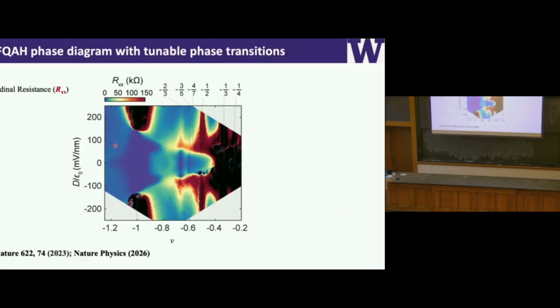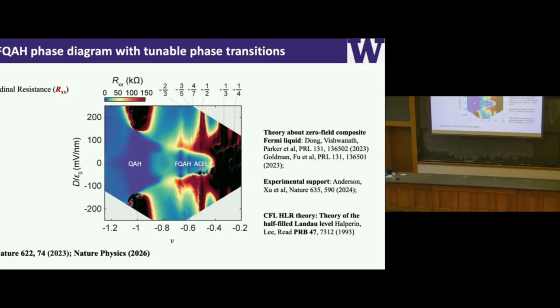And what's nice about the system is that it's highly tunable. What I show you here is a phase diagram, represented by a measurement of RxX. The vertical axis is electric field, and the horizontal axis is filling numbers. The blue color represents vanishing RxX, and the red or dark color represents very large RxX. With this phase map, you can see that we have this quantum anomalous Hall state at the integer filling -1. And we have these fractional quantum anomalous Hall states at the fractional fillings, and then near -1/2, we have a finite RxX, but not quantized, with RxY at the 2h over e squared. So that's actually a composite Fermi liquid state, but at zero magnetic field.